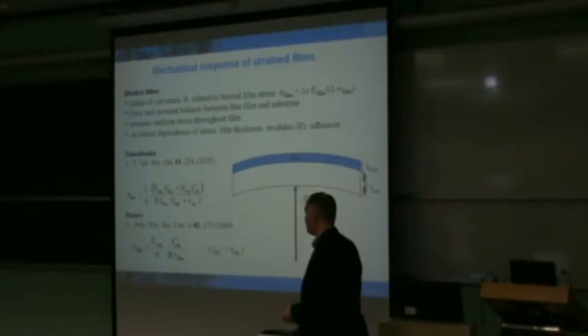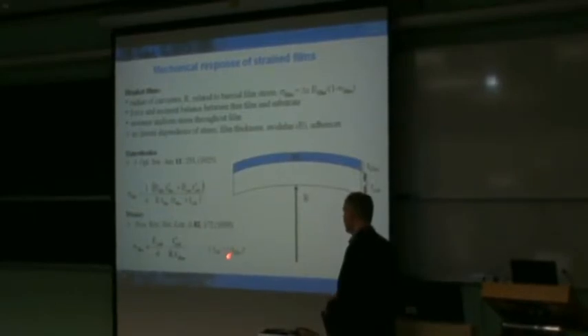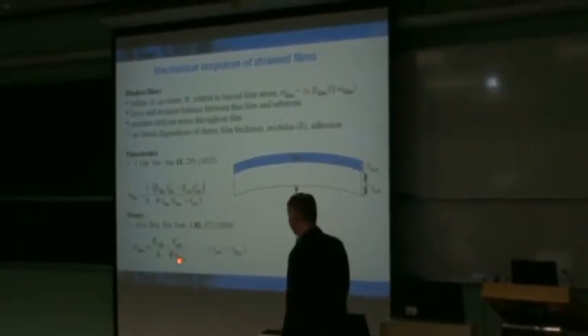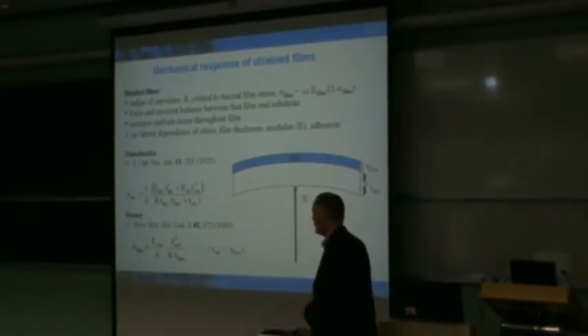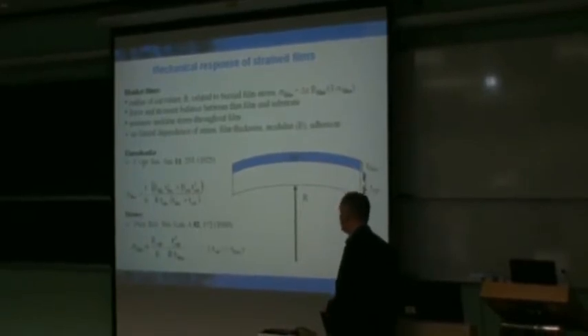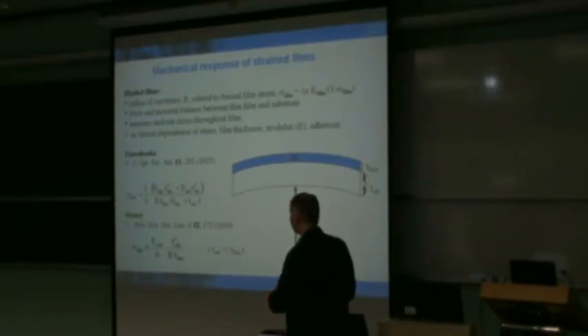And in fact, you can then, by other methods, look at how you can generate from a force moment balance what the stress is within the film. And it's related very nicely in the simplest approximation, where your substrate is much thicker than your film, something that only takes the film thickness as the only quantity, assuming that you know the substrate modulus and the substrate thickness, what that film stress will be. And you can actually do a more complete analysis by incorporating a finite film thickness to show that, yes, you can do this relationship between the film stress and these quantities. So that's fine. You can quantify this effect.